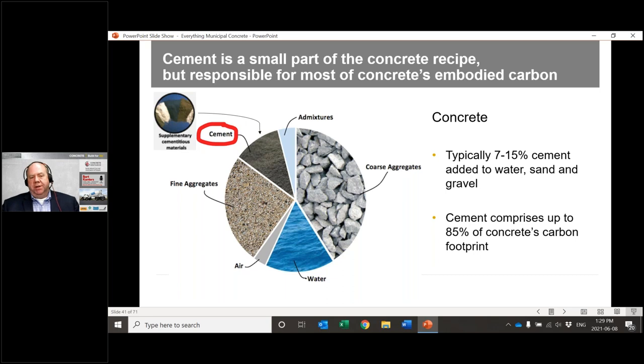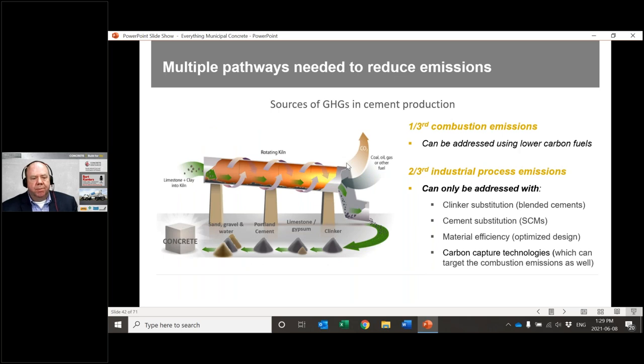So when we jump back to concrete and we look at it, well, what's the component of cement in concrete? It's typically 7 to 15% we're saying here. The material itself is primarily sand and stone. So that's sand and stones making up about 70 or 75%. And then we've got water for municipal applications. We're almost always adding air treatment for freeze thaw protection, and then a small quantity of chemical admixture. But it's that cement component where the majority of the CO2 is coming from.